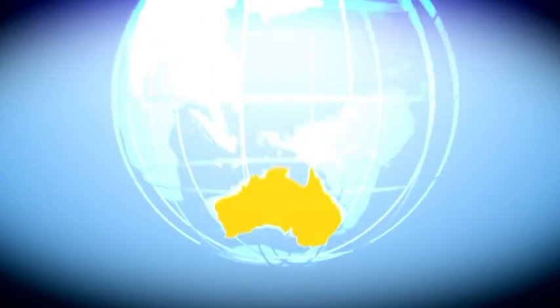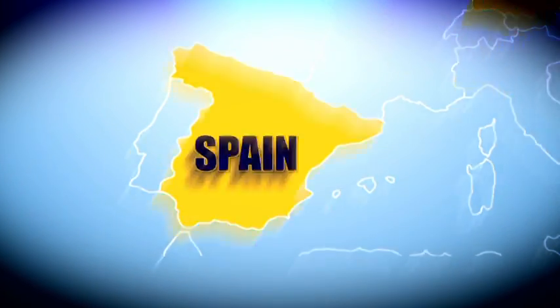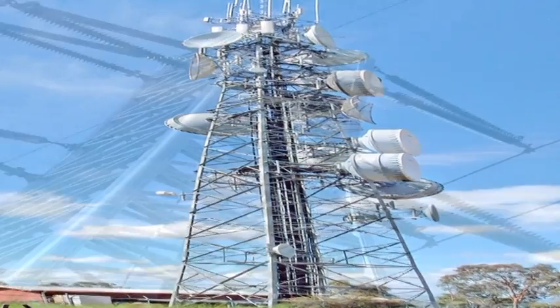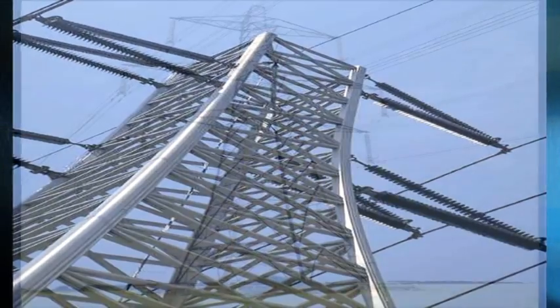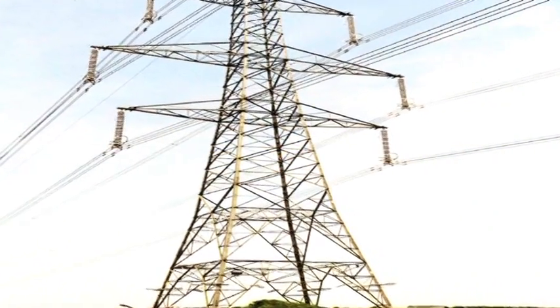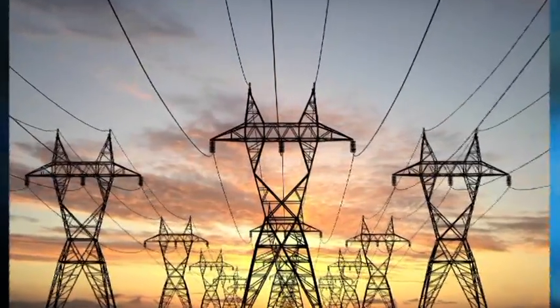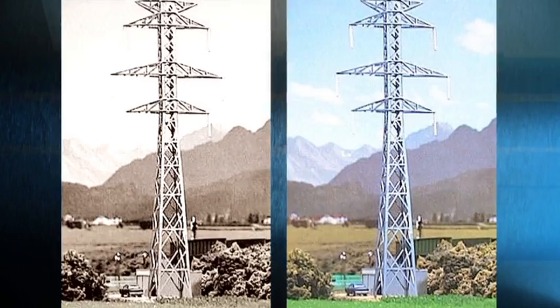This kind of a bonded galvanized coating gives excellent wear resistance and abrasion resistance during transport, during handling, during site operations, etc. Recent studies carried out in Australia, Germany, Holland, Spain and Sweden on galvanized steel transmission towers have documented the outstanding service life that can be expected from galvanized coatings. The towers erected between 30 to 60 years ago still have some of their original coating and are expected to remain corrosion-free for years.